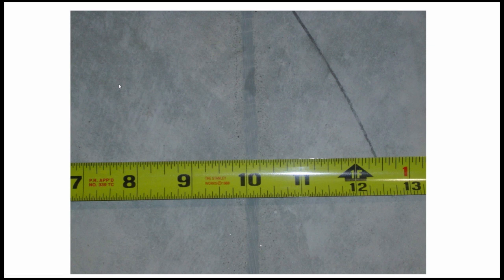What I was mentioning before about the freezer drawdown, in our instance for the joint filler, we did use a polyurea. The one benefit or situation where you might want to consider using it is an instance where you have freezing or lower installation temperatures. In this instance, they were beginning to do the freezer drawdown for the freezer itself to the freezing temperatures. And had we used an epoxy prior to that, my concern was that the slab itself was going to shrink as it was exposed to the freezing temperatures and would shrink away. And the epoxies don't have the lower installation temperatures that polyureas do. In this instance, we did not have issues with the polyureas, but I'll talk a little bit later on about an instance where we did.